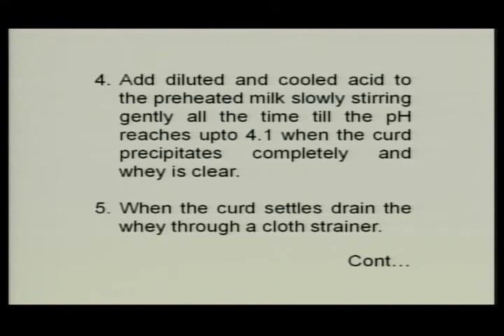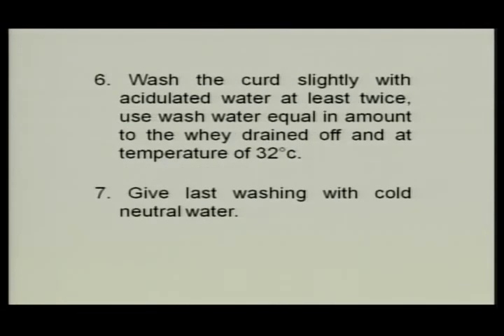Allow the coagulum to remain at that temperature for a few minutes so the curd settles completely. Drain the whey using a cloth strainer. Then wash the curds with acidulated water at least twice so that all whey sticking to the curd is removed. The quantity of wash water should be equal to the quantity of whey drained off, and the wash water temperature should be around 32°C. Give a final washing with cold neutral water.